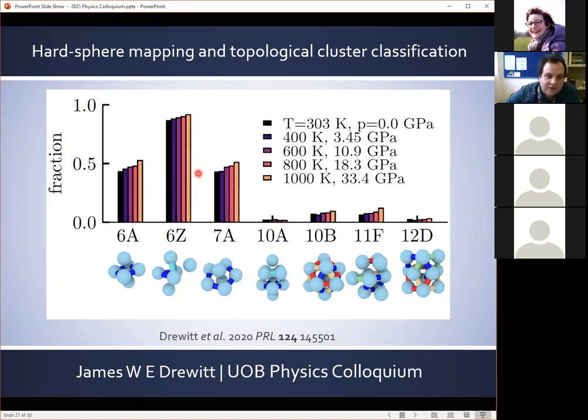And so with increasing pressure and temperature, the abundance of these larger motifs increases, and particularly this 10B unit, which is a five-fold symmetric, partially icosahedral unit, and this crystalline 11F unit stand out. Although still quite low concentrations, their abundance almost doubles from low to high pressure.